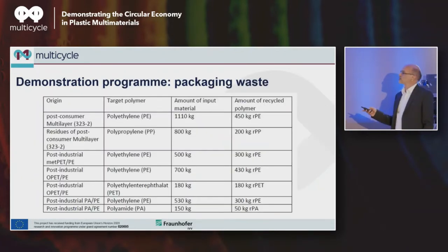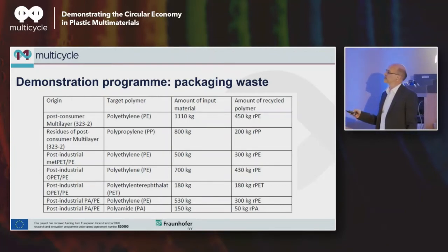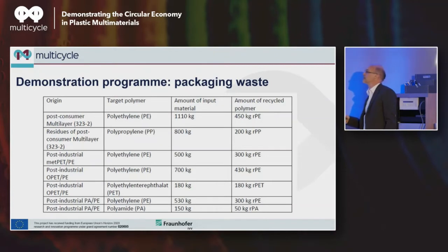This is the demonstration program in operation that we went through. You see here we produced first polyethylene from post-consumer multi-layer material. Here, exactly what I told you, 1110 kg of feedstock, and it's not only the yield out of that, it's also the losses in that production. In the end, we ended up with 450 kg. Since when it really started to work quite well, we had to switch to the next one.